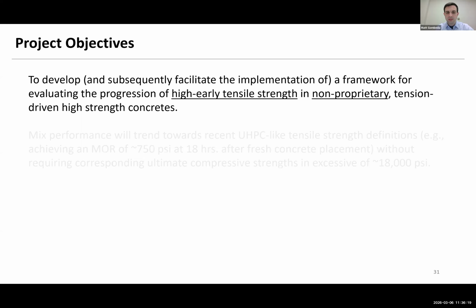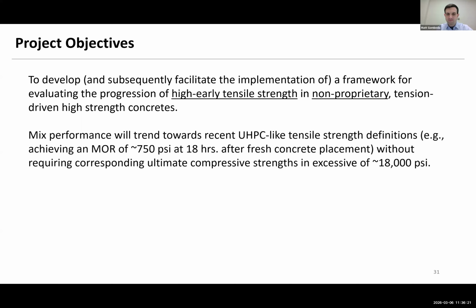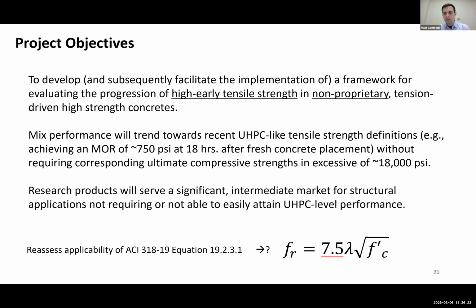In the past, we're so used to this equation down below where we have a set compressive strength and then we're asked to calculate the flexural strength as a result of that number. But we wanted to move towards a performance-driven flexural strength mix design approach so that we can target a specific modulus of rupture of about 750 psi at about 18 hours.